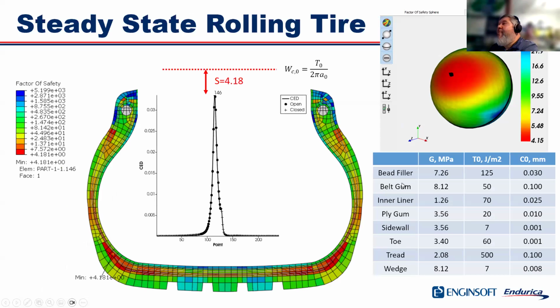Here's another example of where you might use the safe life analysis. In this case, this is for a tire rolling under steady state. And what you can see is that I've colored the elements in the cross section of the tire. It's a 3D tire model, but we've basically followed each streamline around the tire and computed a safety factor for each streamline. And then we've just colored those on the cross section of the tire. So you can see the smallest safety factor in the tire is near the tire's belt edge. In this case, for these conditions, we have a safety factor of 4. So this would tell you that this tire under these conditions could be expected to not develop cracks.